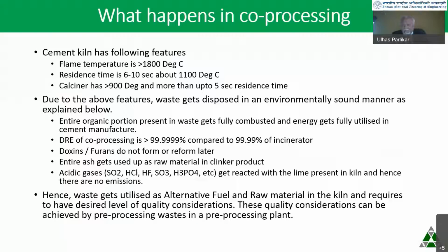Now, when you combust the materials, you may end up with sulfur dioxide, hydrogen chloride, hydrogen fluoride, sulfur trioxide, H3PO4, and gases of that kind. Most of these acidic gases react with the limestone which is coming down, and while coming down, it is getting heated, and it gets calcined into calcium oxide. It's a very fine powder, so it has a very large surface area, and with this high temperature, large surface area, and intense mixing because of the counter current flow of gas and the solids, you get a beautiful interaction and reaction between the acid gases and the raw materials, and therefore no acid gases get released or left out from the cement kiln.